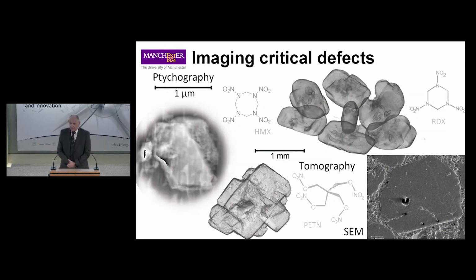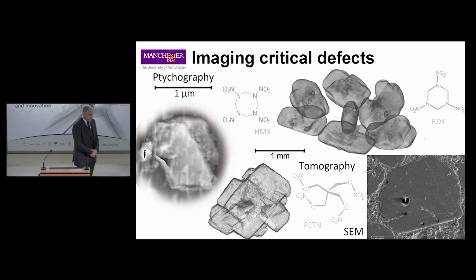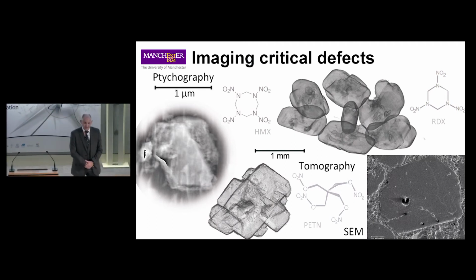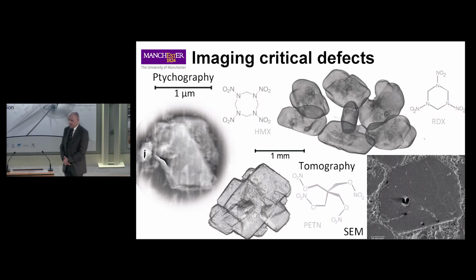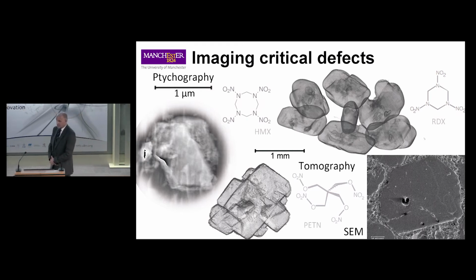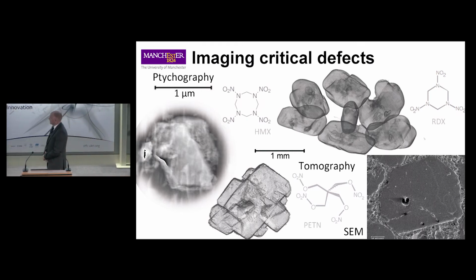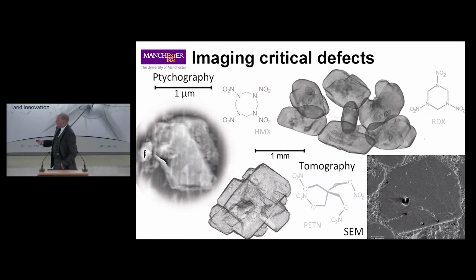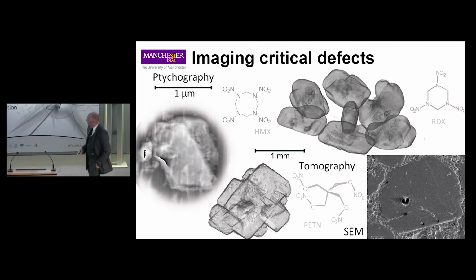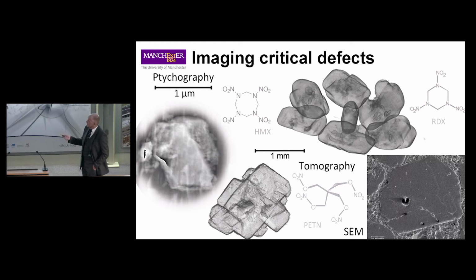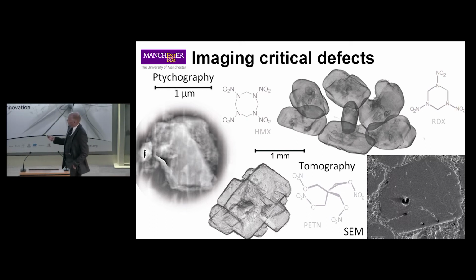Okay, now for an example. I'm going to choose a material that responds not only mechanically, but chemically to an individual pulse that hits it. Here is an explosive crystal. And with the excellent facilities in I-13, we can observe that with ptychography down to length scales of around 50 nanometers. And we can see a crack there propagating through that material at that length scale.